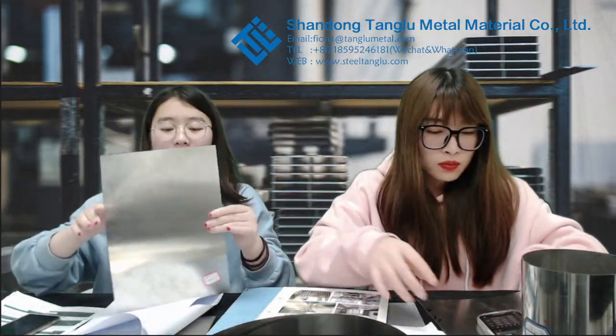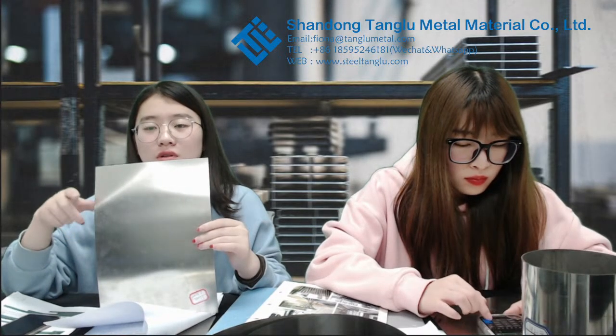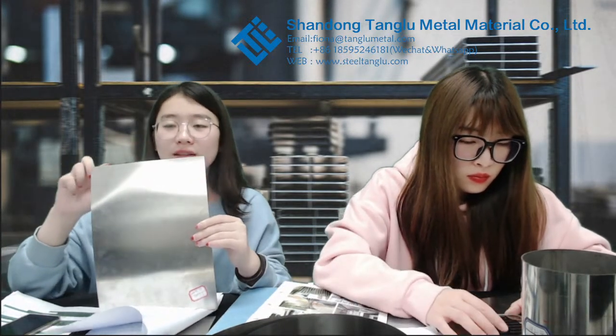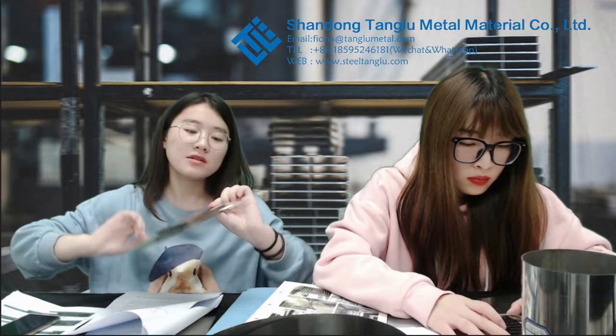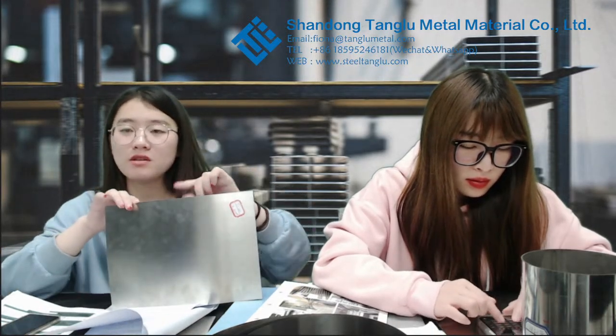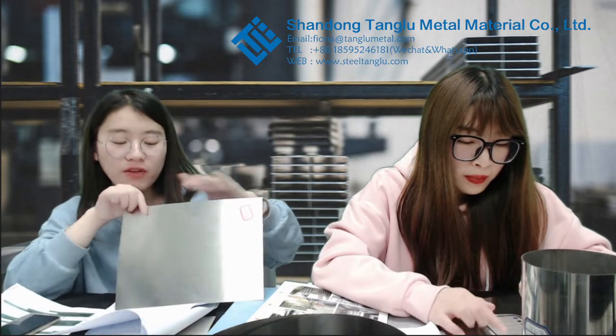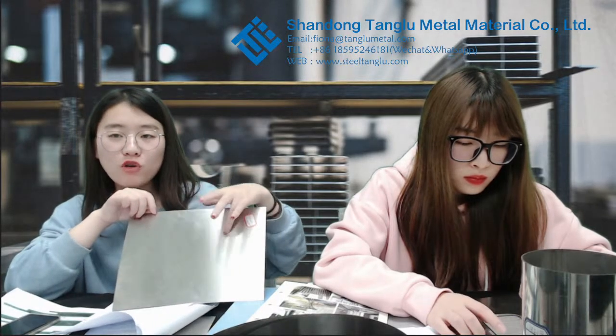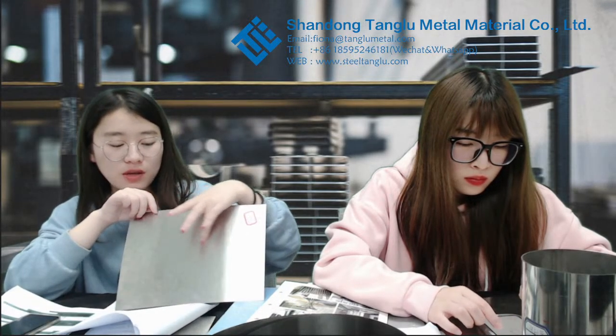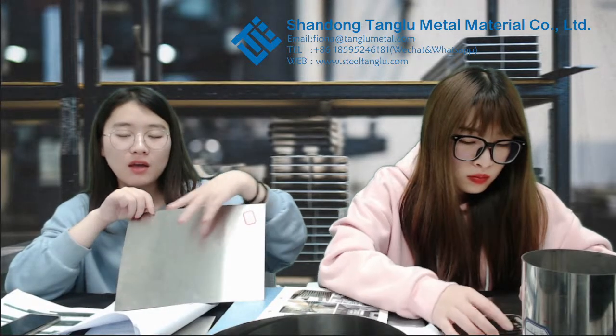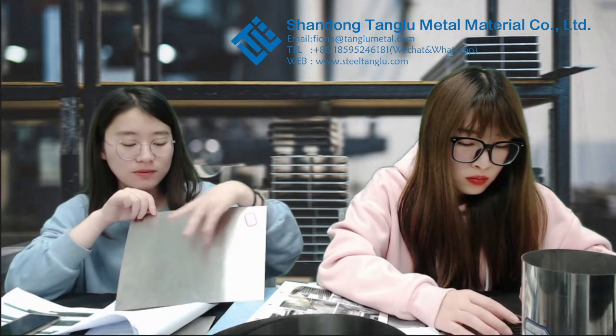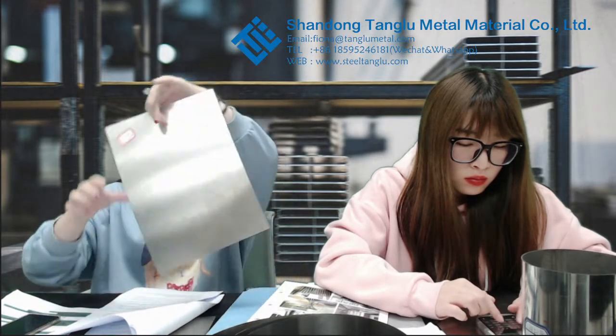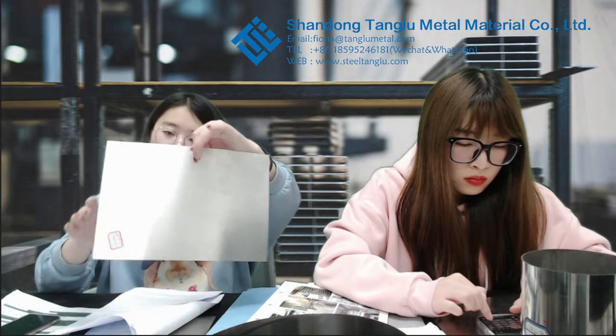Yeah, this sample is a 201 stainless steel plate, and the thickness is around 0.34 millimeters. Yeah, and we can observe that the surface is also very bright and smooth. From touching it, we can judge that it is very smooth. The edge is also very smooth. Yeah, this is just one sample.